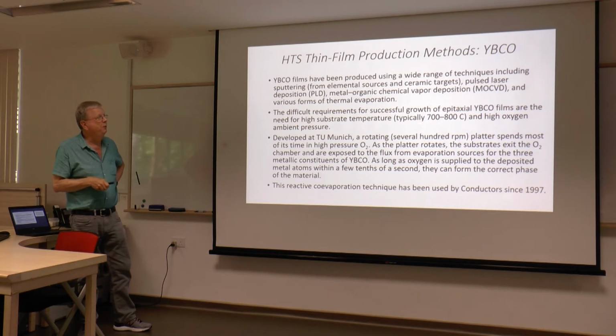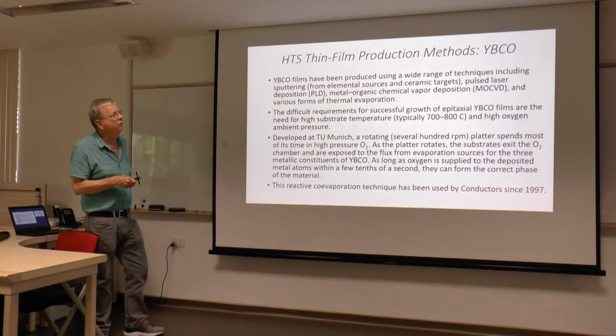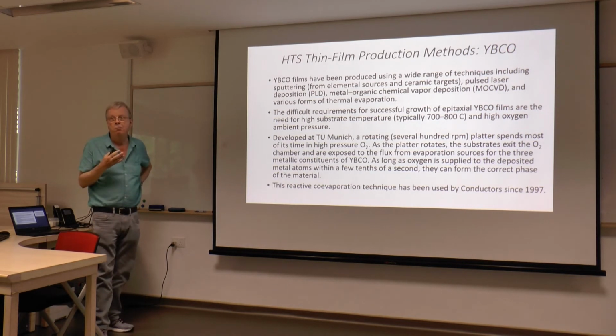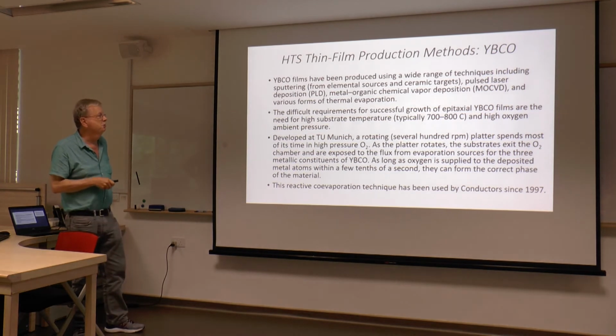There's the problem that you need a rather high substrate temperature, and you don't want interdiffusion between your substrate and your film, because then you'll just get dirt in there, and it won't be a good superconductor. The other problem, which is a very often not covered topic, is that the good TCs need an oxygen content of 6.9 and higher. So you really need to work at getting the right oxygen stoichiometry here. If you make a poor film, the oxygen might be 6.3, 6.5, and the superconducting properties are poor. So you need to get the oxygen concentration up.